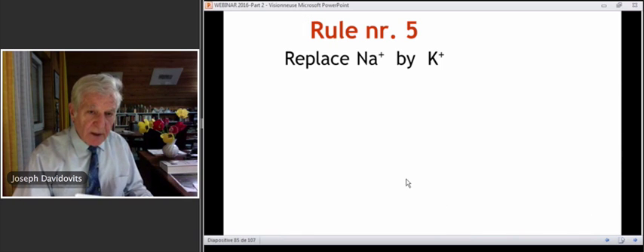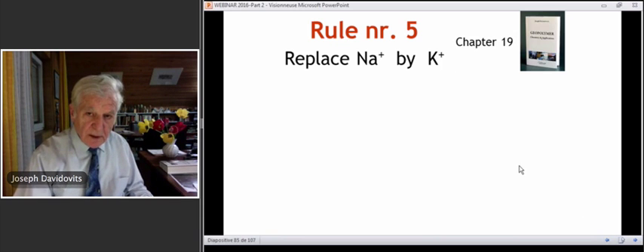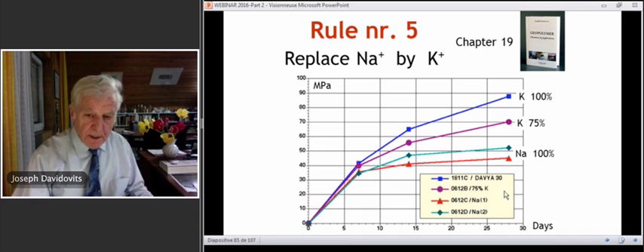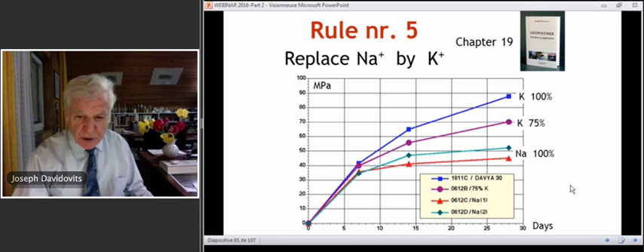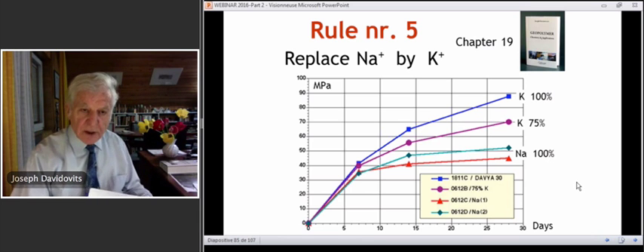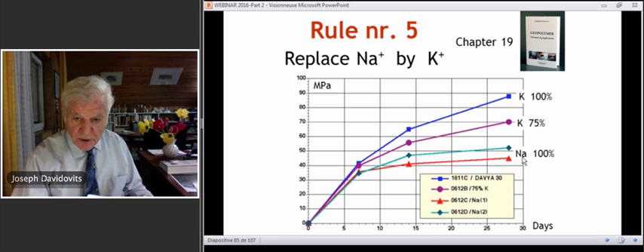Rule number 5, replace sodium by potassium, if possible. Chapter 19. Here you have two types of geopolymer cement, potassium-based and sodium-based. Same molar ratios, just by replacing sodium by potassium. 100% potassium, you reach 90 MPa at 28 days. 100% sodium, you reach 45. That is half of the potassium silicate.